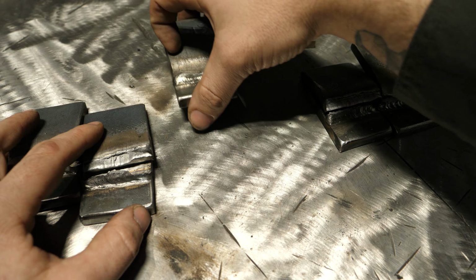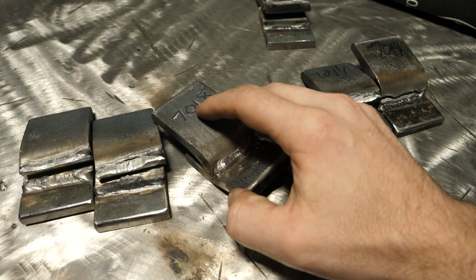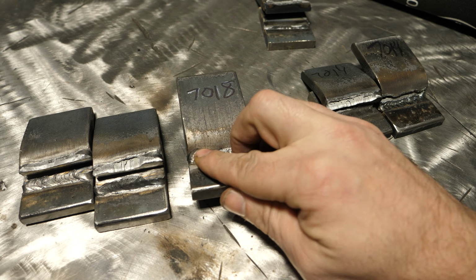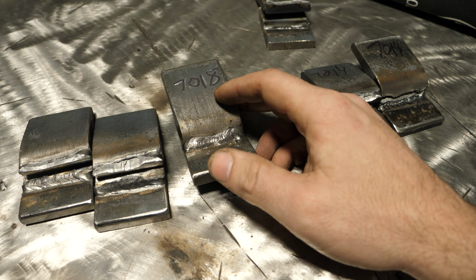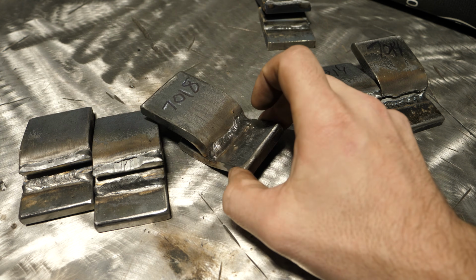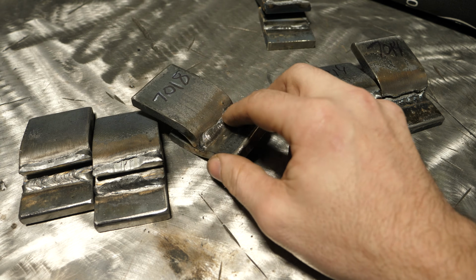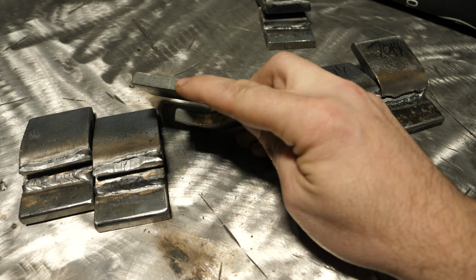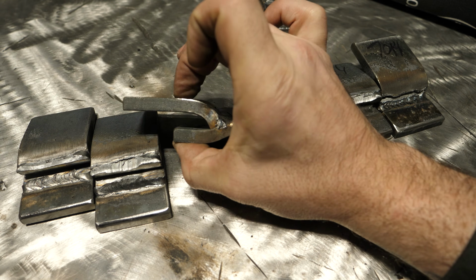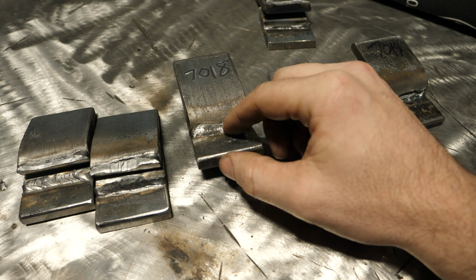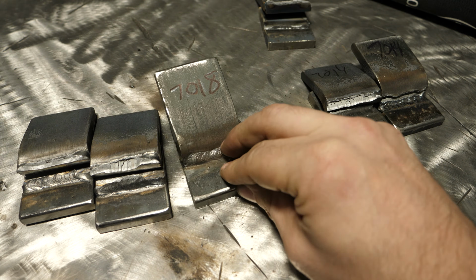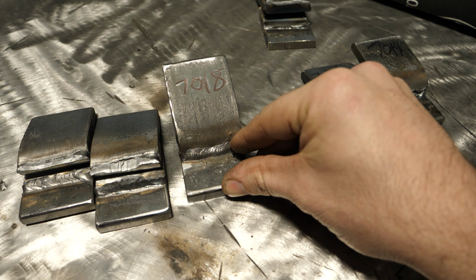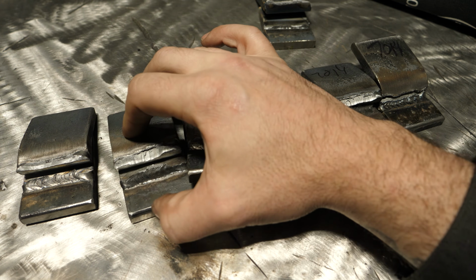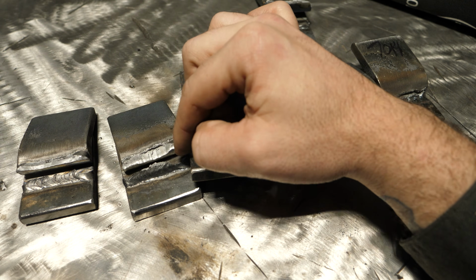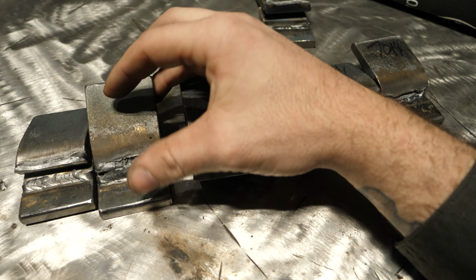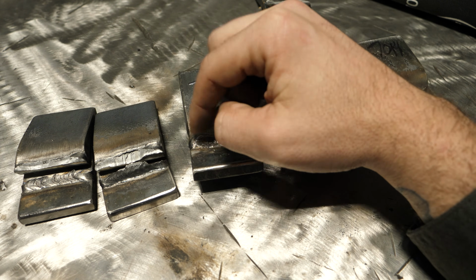And to contrast it to the 7018, I've done, I don't know, 3 or 4 or 5 of these on camera, and I've done at least, I don't know, 8 or 9 more of these off camera just for random things, and I have yet to have a 7018 fail, okay? And you can see how much more this is bent back, and I even put enough pressure to bend these two together. I mean, you were talking over 9 tons, and this weld still did not fail. It even has the start of a crack or a crease there where it's pulling against it, but it has not given up. These guys here, like I said, even if I didn't have that little bit of underfill there, it still would have failed and it still would not have held together like this did.